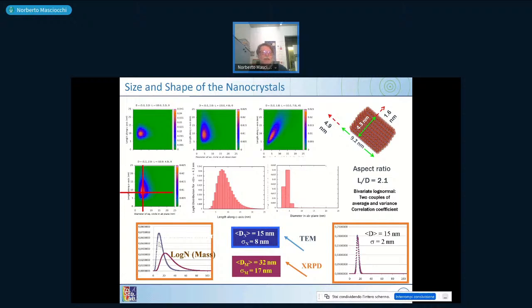In fact, this distribution represents the same material. The one only counts how many particles have a certain size, and the other one is how many particles have a certain mass. And because the mass goes to the cube, not to the square of a size, there is a shift to higher values for the log mass. If you take the same sample at the TEM, you can get a distribution in number with an average of 15 nanometers and a width of distribution of 8 nanometers. The very same material obtained by X-ray powder diffraction gives you 32 nanometers and 17 nanometers.